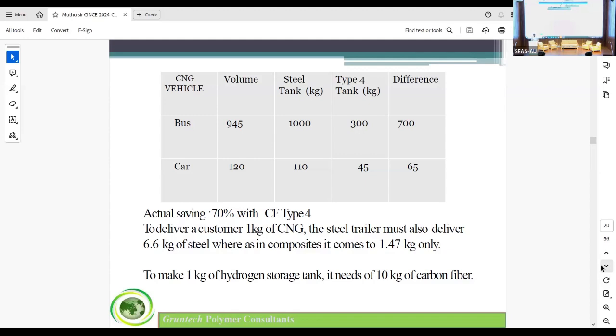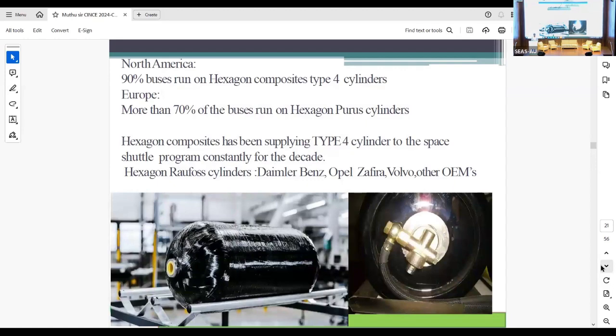To make a hydrogen storage tank, as an approximate figure, it takes 9.5 to 12 kg of carbon fiber per 1 kg of hydrogen held. To have 1 kg of hydrogen storage in your tank, you need at least 10 kg of carbon fiber. In North America, 90% of buses run on Hexagon Composites Type 4 cylinders. Hexagon started with LPG, succeeded in the North American and European markets, and then started penetrating the Asian market.